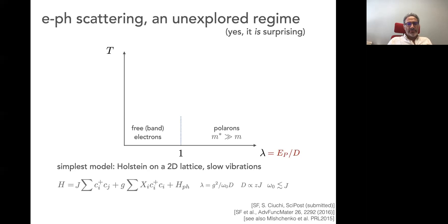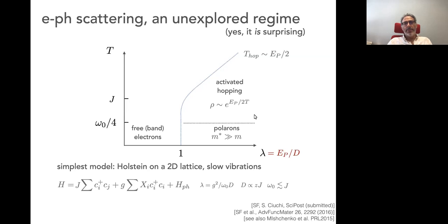If you're at low temperatures, this is all well known. At weak coupling, you are in a free or almost free electron regime, and you can apply band theory. Then when you increase the coupling, you hit some critical value where you form polarons. These can also move as extended waves, but with much larger effective masses. When you increase the temperature, in this polaronic regime, you go from a tunneling regime in transport to activated hopping. And this is where Marcus theory works.